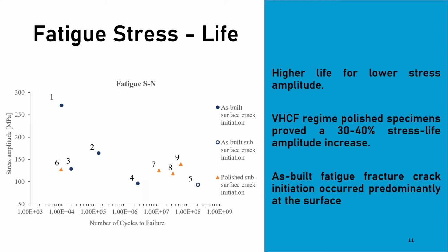With the polishing sequence conducted, and the microstructural analysis and basic static mechanical properties obtained, the fatigue stress life experimental procedure was conducted. The stress life results show that the polished specimens proved a 30 to 40% stress life increase. Also, as-built specimens show predominantly fatigue crack initiation at the surface.